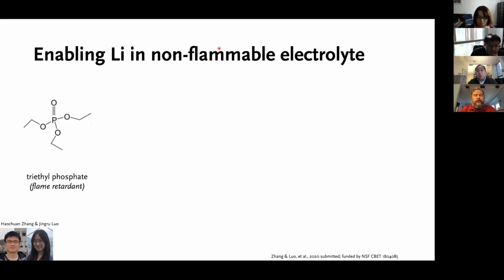So they wanted to look at non-flammable chemicals. One of them would be this organic phosphate. In this structure, phosphorus can help capture hydrogen radicals. Hydrogen radical is a very important intermediate in the chain reaction of combustion. One of them is triethyl phosphate, in short, TEP. And this has been used as a flame retardant in some battery studies by mixing it with existing carbonates.